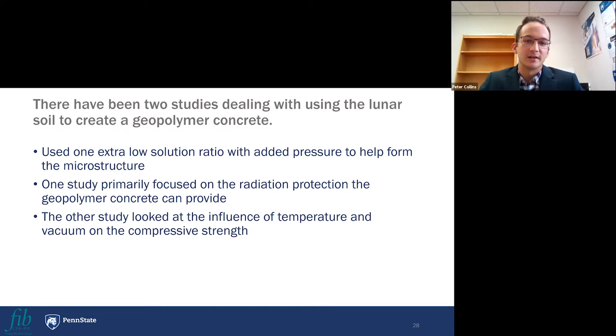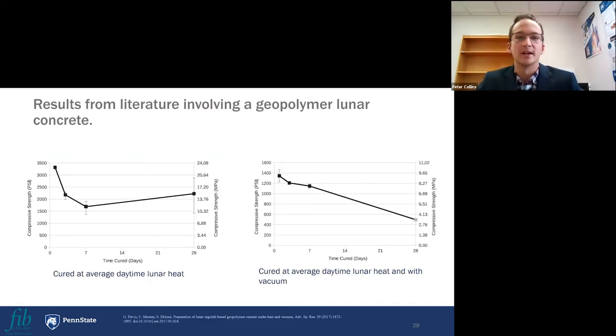The one study, they made a couple cubes and then they characterized its basic properties in order to model the radiation protection. And they found that at a certain thickness, the radiation protection, again, because you have no atmosphere on the moon, radiation is a huge concern to astronauts. At a certain thickness, the geopolymer concrete provides more than enough protection from the solar radiation. And then the other study looked at the influence of temperature as well as the vacuum environment on the compressive strength of the lunar geopolymer concrete. And I'll show you those results real quickly.